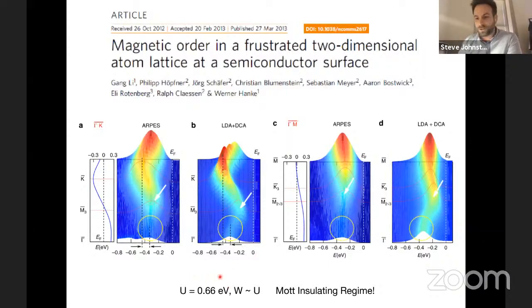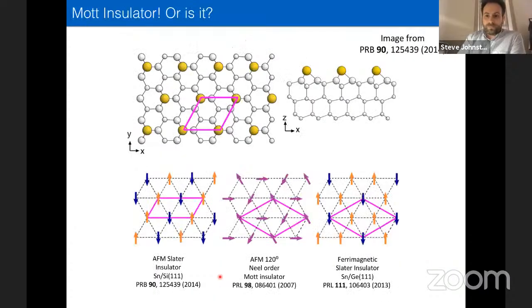So again, the U is on the order of about 660 meV, and the bandwidth of the system is about half an eV. So again, U over W is order 1, which again places it squarely in this Mott insulating regime. So yeah, this paper came out. They were arguing that the system is indeed a Mott insulator, but then of course there were a number of other proposals that came out saying, well, no, wait, the system could be a Slater insulator.